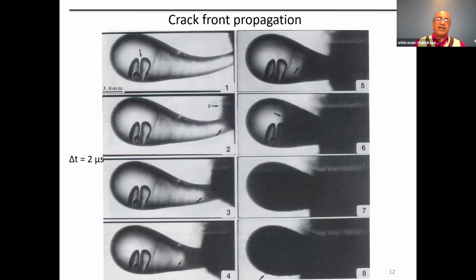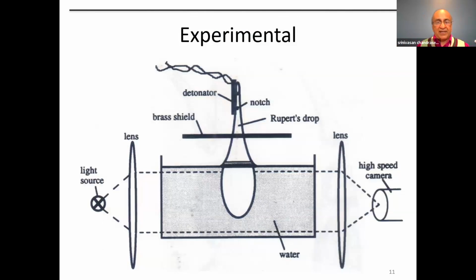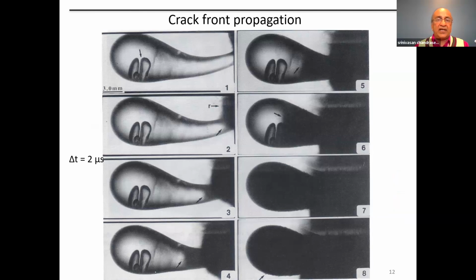So the important thing here is we need to see the inside of the drop, and it turns out when you just light it up like what is shown here, it's hard to see the interior. So what you need to do is, between the light source and the drop, insert a sheet of tracing paper or some sort of ground glass. Then the light source will be made more diffuse, and that trick lights up the interior. When we first reported these experiments, we left out that detail so that we had the advantage of being able to use that to do more experiments before others reported.